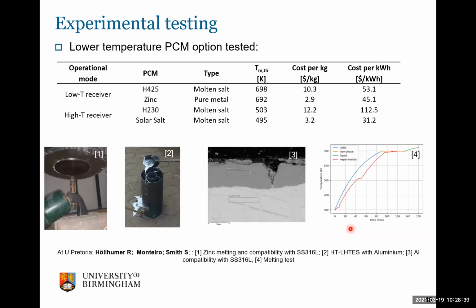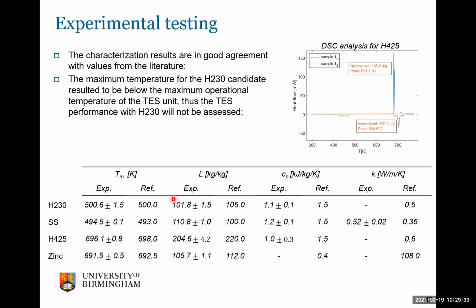Where we are at the moment, also in close collaboration with the people at the University of Pretoria that are part of the project, is experimental testing at kilogram scale of the options that we are currently considering. A couple of molten salts that are actually commercial products at the moment are the typical so-called solar salt, which is a binary mixture of salts. And on the metals, we have been testing aluminum as well as zinc, where the zinc option has to be developed also with the need of specific coatings for the components to prevent the corrosion issues I mentioned before. So even though this is a slightly lower temperature application than the original one, the challenges remain quite relevant, although they're more manageable, as I mentioned initially.